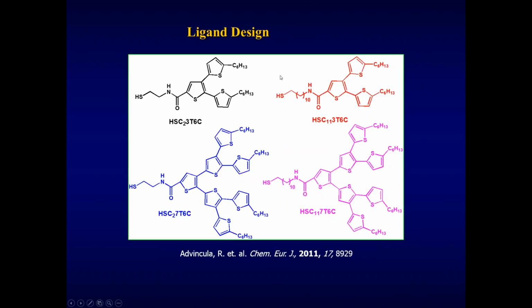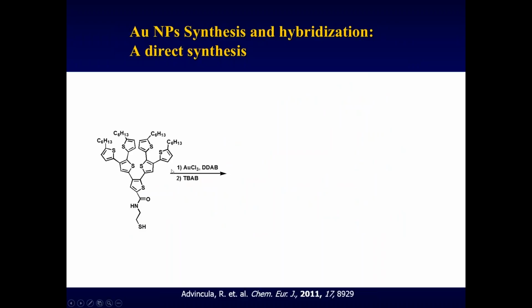So in this case, we prepared a very simple device of this cadmium selenide capped with polythiophene dendrons, and we were able to observe a photocurrent behavior based on this IV curve with an aluminum cathode and ITO anode configuration. Now let me turn to another example of how we've used dendrons to cap gold nanoparticles.